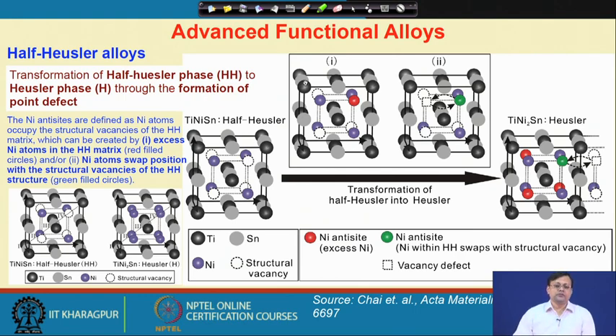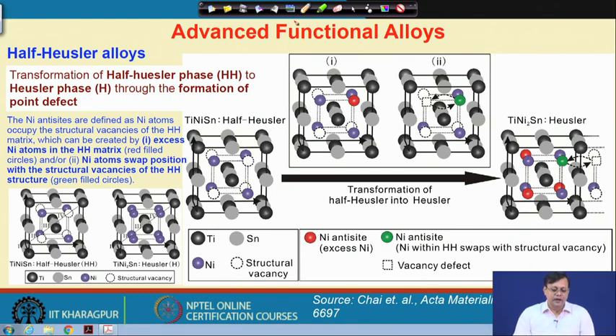However, the switching between the half Heusler phase and the Heusler phase we can identify by considering the formation of some point defect. This is quite simple, because I have shown you that the C sublattice is missing in a half Heusler phase, and here there is a need of a structural vacancy. So, titanium nickel tin is a half Heusler compound, and titanium nickel 2 tin is a Heusler type of compound. In this particular case you can see that there are some structural vacancies present.